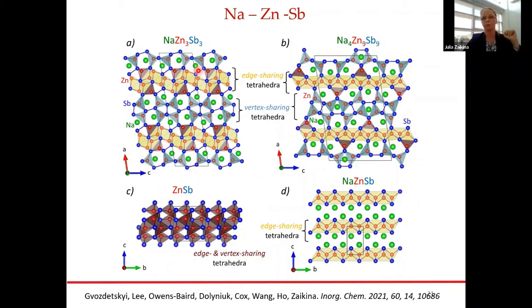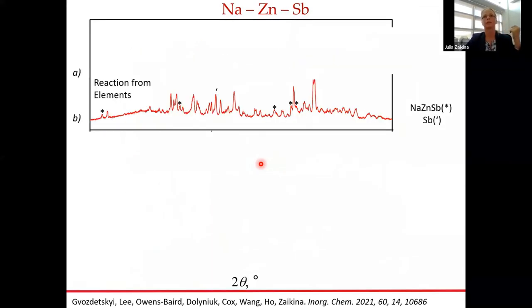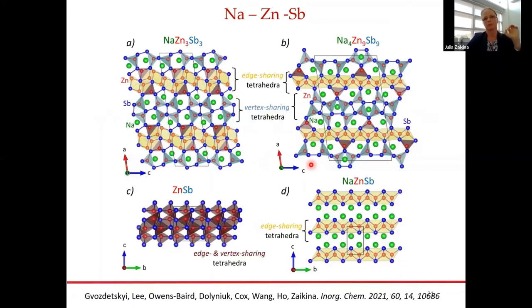And again, with these compounds, I want to highlight our hydride synthesis because of this excellent mixing we can get by using the powdery hydride precursors. We can really target the specific compositions, because those 2 phases are sort of similar in composition. Yeah, if we plot them on our compositional triangle.